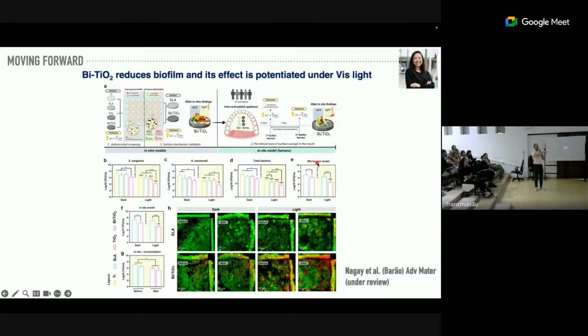We use a microcosm model where we use saliva as an inoculum, and we have a growth condition using aerobic and anaerobic condition. I'm going to show this model at the end of my presentation. And then at the end, you have a biofilm composition that is similar to peri-implantitis. And we have an effect under visible light, especially for that group that has a photocatalytic action under this visible light. We also ran some experiment in situ. We use a palatal appliance in patients, and the patient is going to use this palatal appliance for 3 to 7 days. I don't remember in this study if it was 3 or 7.